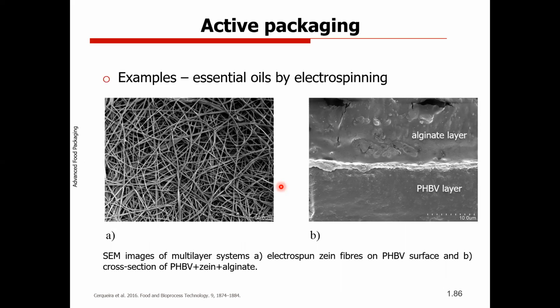Another of the examples is essential oils that can be added by electrospinning. If you remember, we are able to make fibers and layers on the surface of different substrates. Here it was not on paper, as I showed before, but here we try to do two things. We try to encapsulate essential oil in nanofibers. In this case, this fiber was from a protein, zein, dissolved in ethanol, and then we make the fibers above a film of PHBV. PHBV is a polyhydroxybutyrate, a biodegradable material that has been tested by several companies and is quite interesting for these new sustainable materials. And then we try to evaluate how this essential oil will behave in different conditions.